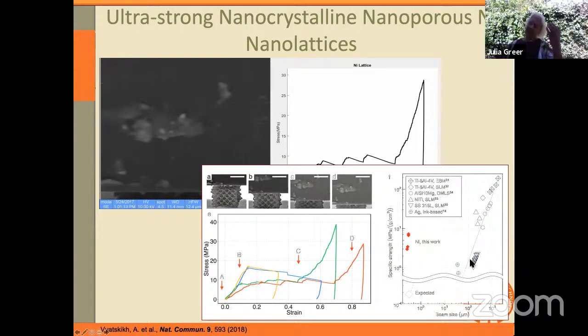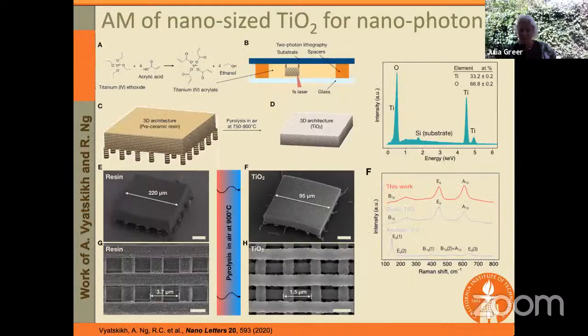So what that tells us is that at our sizes, if we were to just extrapolate this plot, we should be somewhere over here. But when we plot the nickel, the so-called low quality nickel of our work, and compare its specific strength to that of other available processes, what we can see is that its strength is comparable to something that's about 500 microns in dimensions. And so what we're learning is that we don't sacrifice the strength. We don't have this rapid decrease in strength. And effectively at the nanoscale, materials become much more robust against the defects. So this is a very promising result.